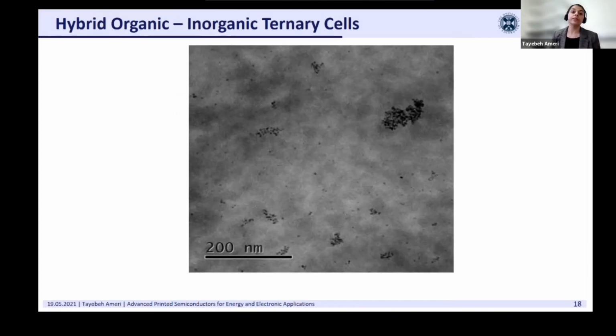One of the biggest issues and challenges with the hybrid system is that when you introduce inorganic quantum dots in high content into the organic host system to have enough absorption and improvement in device performance, they start to agglomerate and have a negative impact on the nanomorphology and the charge transport of our host system. So we were thinking about how to address this issue.